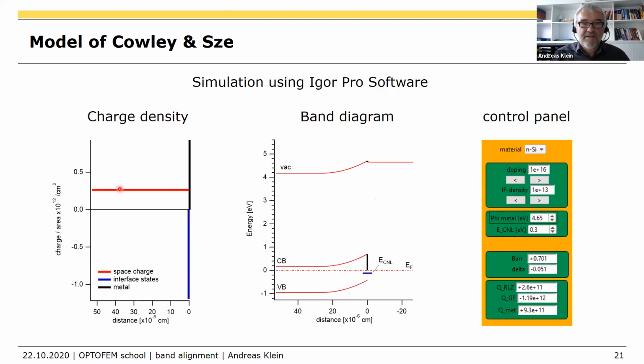So I did some modeling with my highly liked IGOR Pro software. You will see this soon. What do you see here? The plot of the charge density. So this is our space charge. The blue one is the charge in the interface states, which is negative here. And the black one is the compensating charge in the metal surface. So this is now the band diagram: vacuum level, conduction band, valence band, and the charge neutrality level. And this is the control panel in my simulation where I can adjust the doping concentration, which I will not do, that's not important, but I can adjust the density of states at the interface, so the degree of Fermi level pinning, and I can adjust the position of the charge neutrality level and also the work function of the metal.